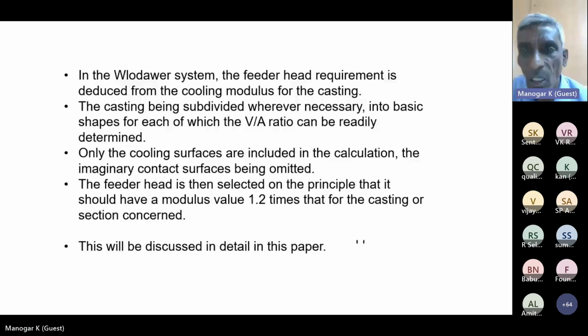In the modulus system, the feeder recommended is deduced from the cooling modulus. The casting is subdivided wherever necessary into basic shapes, for each of which the volume-area ratio can be readily determined. Only the cooling surfaces are included in the calculation, the imaginary contact surface being omitted. The feeder is then selected on the principle that it should have a modulus value 1.2 times the casting modulus. This will be discussed in detail.